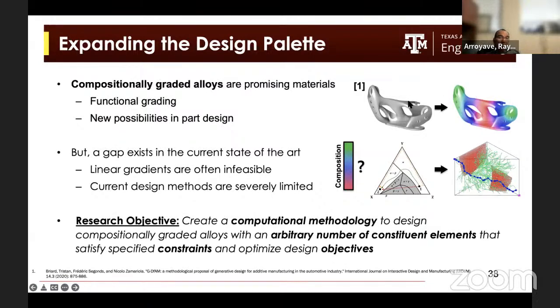So for example, if you're 3D printing a turbine blade, maybe you want to make the surface of the blade oxidation resistant, but you want to maximize the creep strength, or the strength at high temperatures, in the core of the blade, right? Clearly, in some cases, you cannot have an oxidation resistant alloy that is also creep resistant, that is ductile, that has high temperature properties and so on in the same monolithic material, right? Because if you want to do that, you probably have to over design and come up with alloys that are good at everything. And clearly that sometimes is not an attractive proposition.